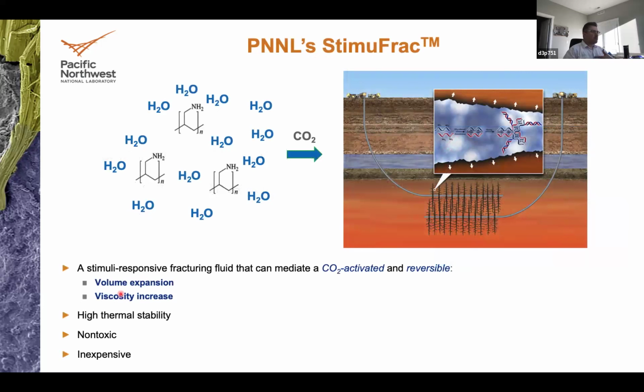So I think probably some of you are familiar with the technology, but for those that are not, this is a very simple schematic of a polyallylamine solution. This is what we call StimuFrac. It's a polyallylamine solution. And for those that are not chemists, this is an amine, and this functionality repeats through the polymer about 200 times for each of the polymer strands. And each of those amines, since they are a Lewis base, can react with a Lewis acid like CO2, CS2, or any other acid gas or acid liquid or supercritical, to cross-link and form a cross-linked fluid.